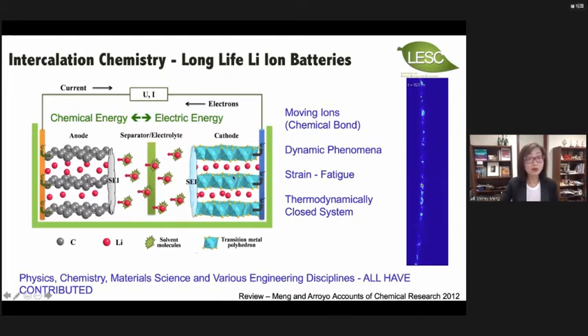The other very important concept in electrochemistry, one must realize, is that when you build this battery with the anode and cathode immersed in the electrolyte, the protective passivating layer, the SEI, is so important, because when you put the battery at open circuit voltage, when you're not using it, the energy retained in the battery must be stable.